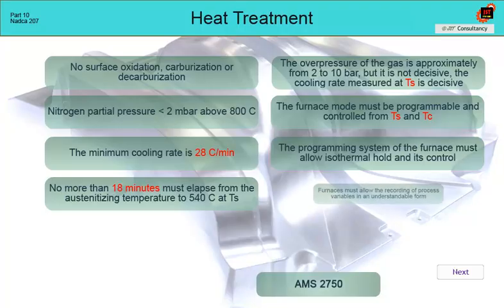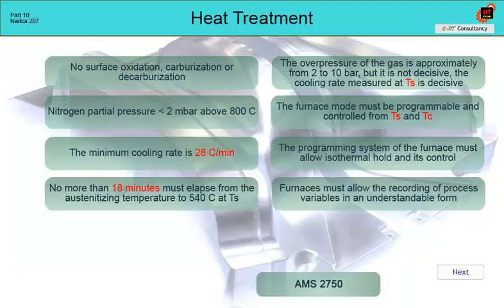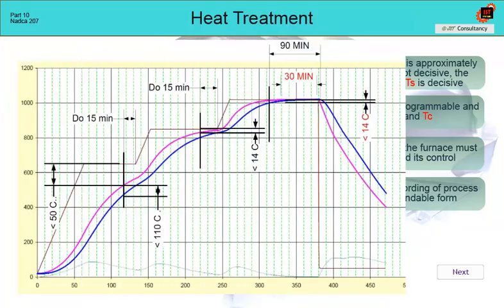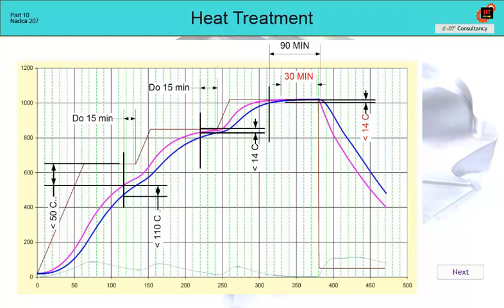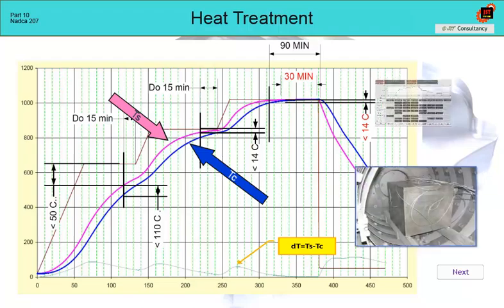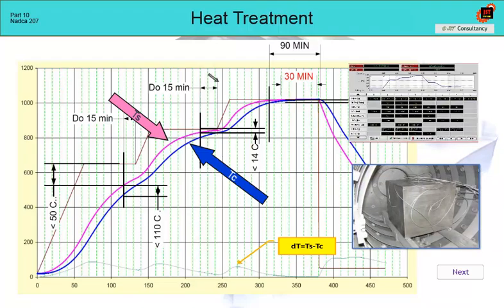The furnace must be able to record data from the process in an understandable and readable form in the entire temperature range. If we project all the requirements of NADCA into the theoretical record from the process, and we have the batch thermocouples correctly placed, then we get the graph of the process according to the picture. Because we have a sophisticated programming system, on the one hand, the temperature of the furnace is correctly controlled, and at the same time the data from Ts and Tc are evaluated so that the part is not damaged during heating, the part is properly austenitized, and it is ready for subsequent cooling.